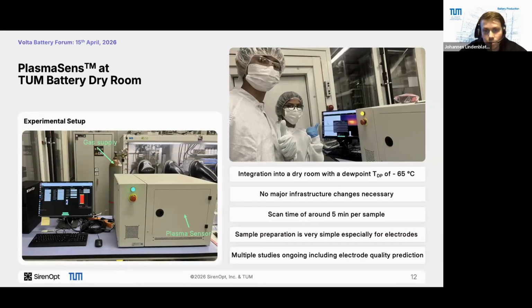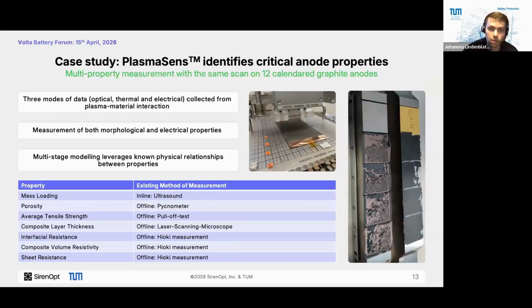The scan time of one sample is around 5 minutes, and it's very simple, especially for the electrodes at the moment, to prepare them. You only need to cut out a little sheet, and then you can put it underneath the sensor and measure multiple properties at once.